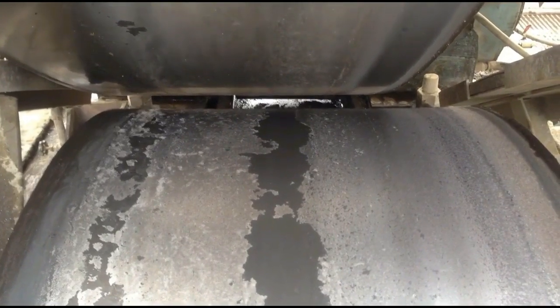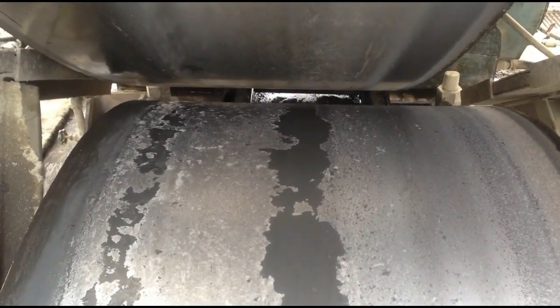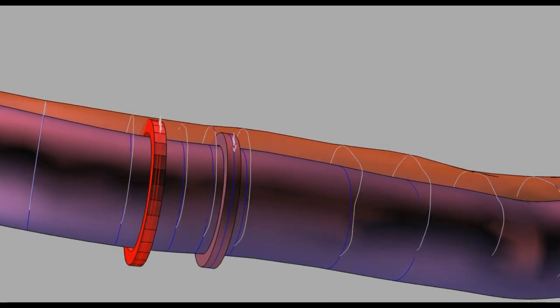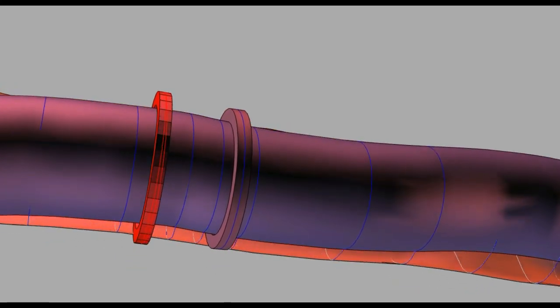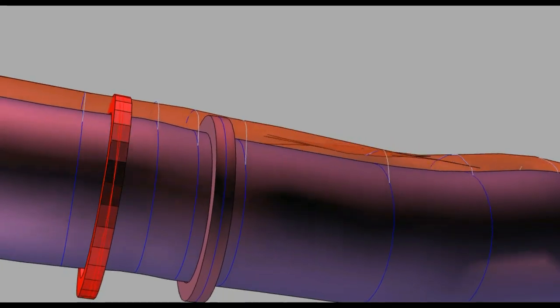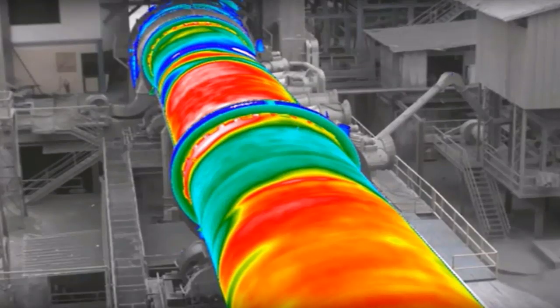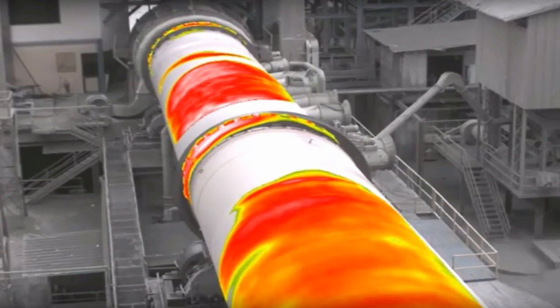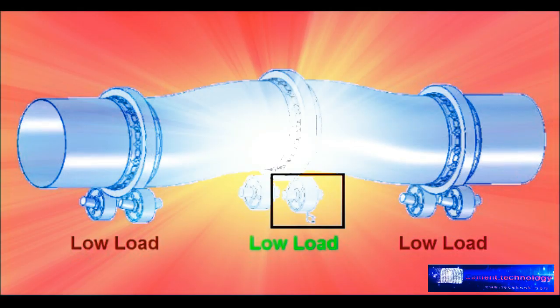On a kiln support roller, the variation of deflection of the roller shafts shows possible cranks in the kiln shell. Cranks are straightness errors in the kiln shell which affect the loads on the roller stations with each kiln revolution. There are two types: the first is a permanent or mechanical crank, caused by plastic deformations in the kiln shell or errors during kiln construction; the second is a thermal crank, caused by uneven temperature distribution or thermal expansion around the kiln shell circumference, most severe close to the middle tire. The load changes caused by cranks can be very strong and overload the tires and rollers, resulting in cracks in tires, rollers, and roller shafts.